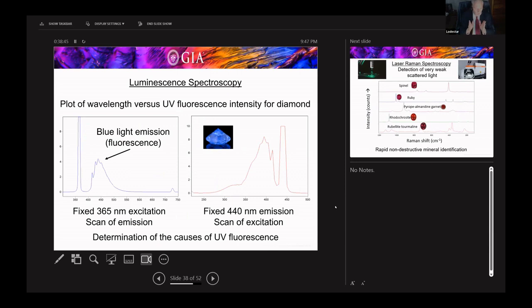We can also do luminescence spectroscopy to understand fluorescence. So colorless to light yellow diamonds often have blue fluorescence. On the left, you can operate this in two ways. You can fix the excitation, which in this case is at 365 nanometers. That peak that goes off the graph is the long wave UV wavelength. And then between 400 and 500, you see this broad peak. That is the emission of blue light excited by that 365 nanometer UV incident light.